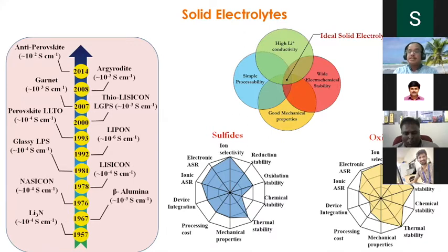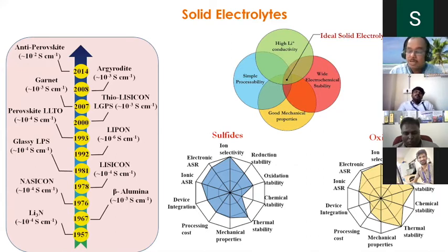But oxides, ceramics, people have quite long experience with. And compared to the sulfides, they have their own advantage: mechanical stability. You can process them very well. So the technology of oxides is a well mature technology. Although the conductivity is poor and they don't have greater properties compared to the sulfides, still there is a lot of focus on the oxides. Most ceramic people and the industry like these oxides because you can very easily scale up the process.